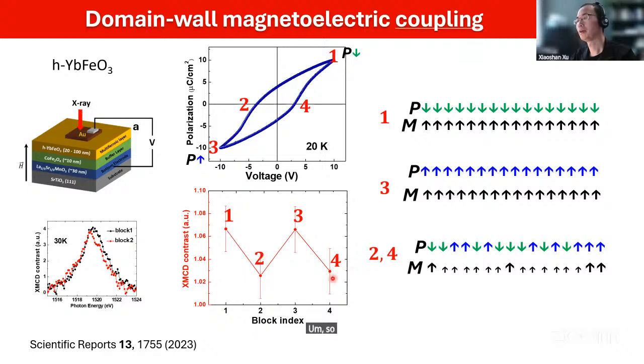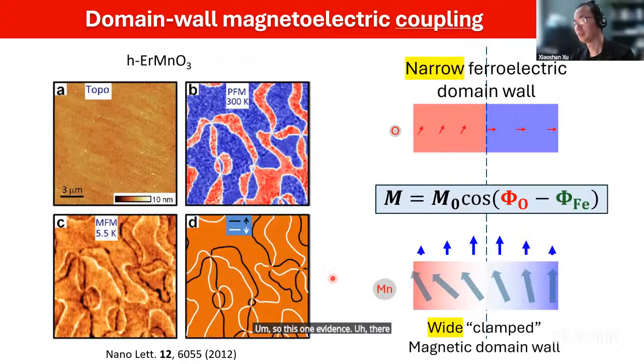So this is one piece of evidence. There's another piece of evidence. It's not ferrite, so it's not iron. I said you can also have manganese in there to replace iron. If you do that, it's quite interesting. The stable case is actually this moment and this one, they are perpendicular to each other.